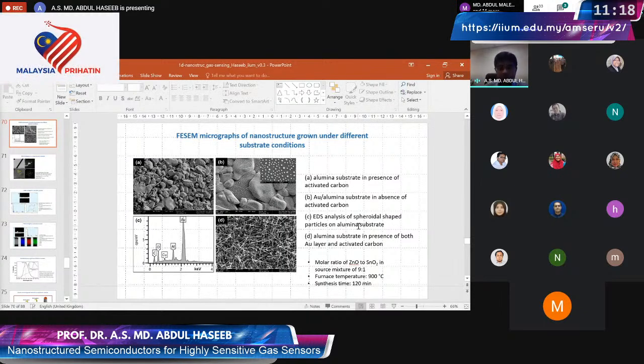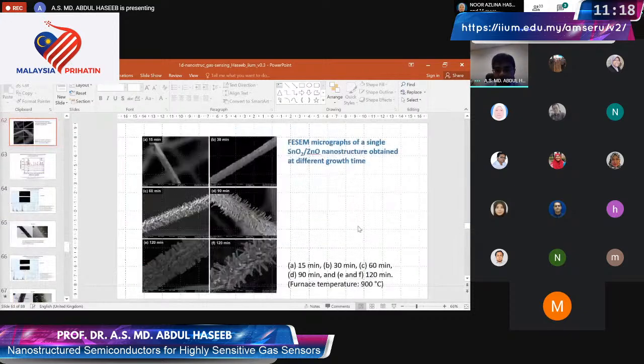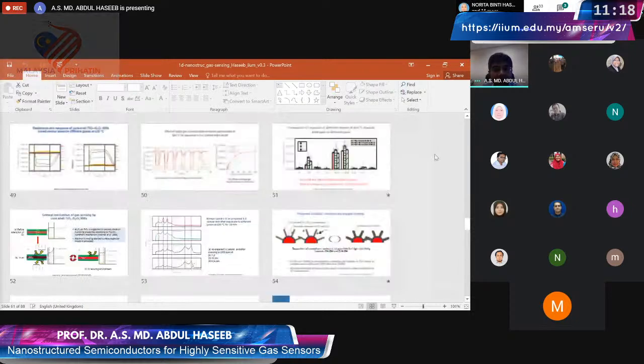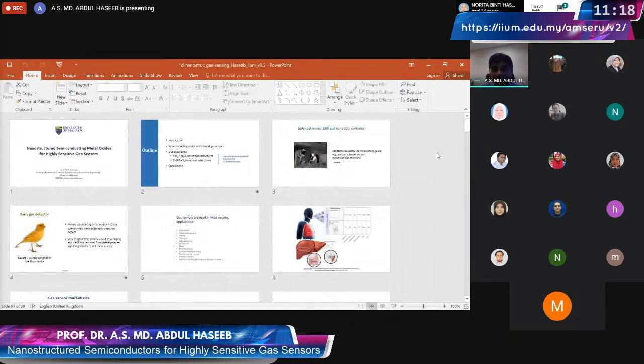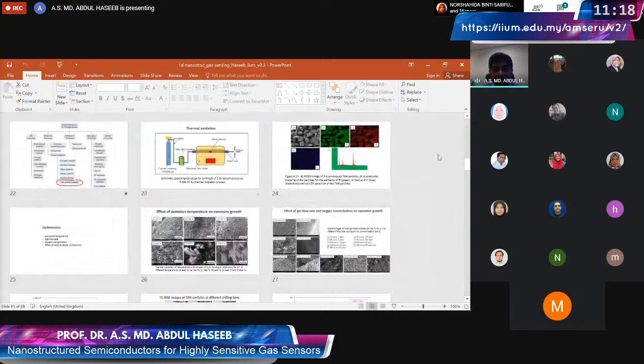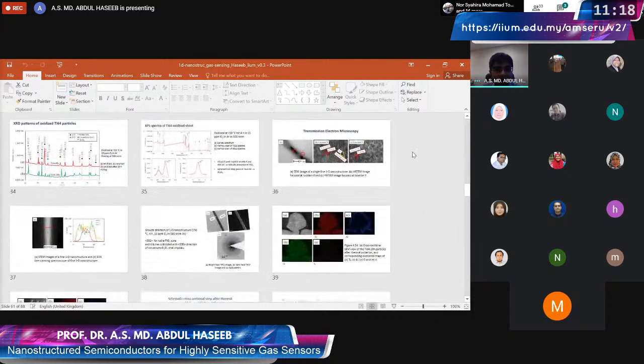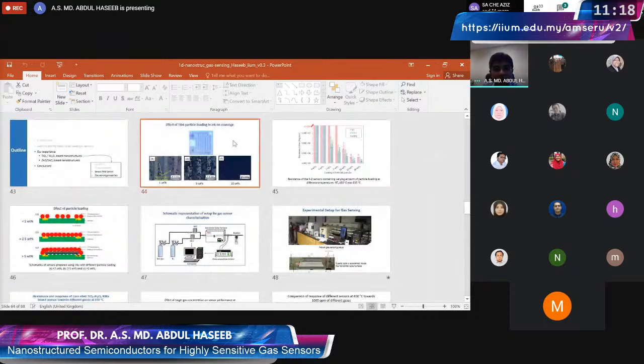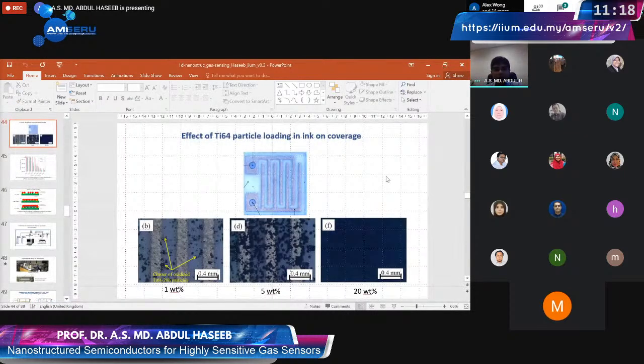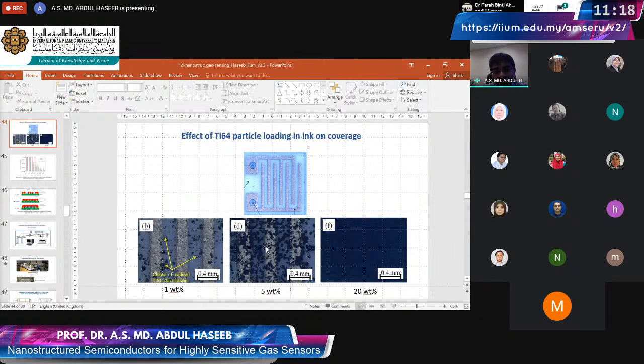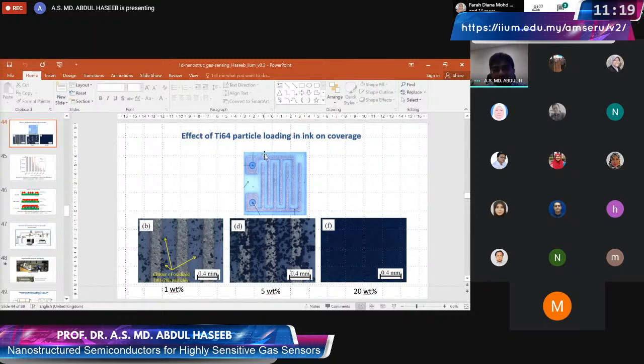What we do here is probably, I can go back, let me show you. We create an ink, which means that we mix the sensing material with a mixture that contains alcohol and some surface active agent. So we create a liquid that we can disperse. The liquid will contain a vehicle and also our nanostructures, and then we drop them onto the surface. And if the viscosity is controlled, then we can get a uniform spread of the material over the surface.